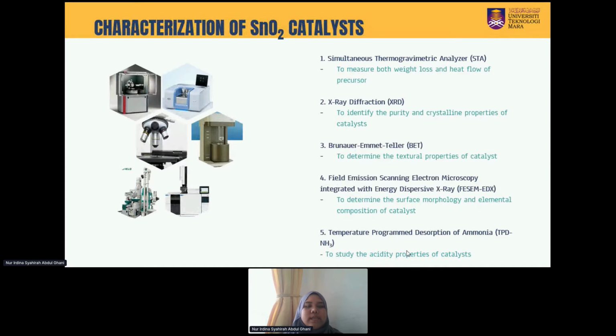The tin oxide catalyst is characterized using 5 different instruments. The first one is the simultaneous thermogravimetric analyzer, STA, to measure both weight loss and heat flow of the precursor. The second is XRD, or X-ray diffraction, to identify the purity and crystalline properties of the catalyst. The third one is BET to determine the textural properties of the catalyst.